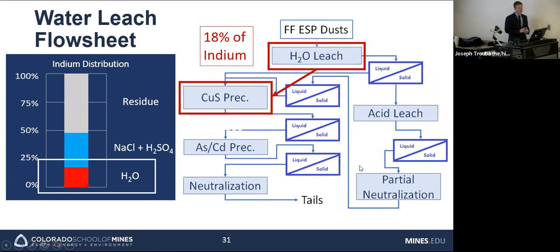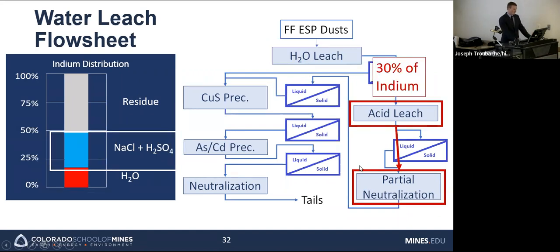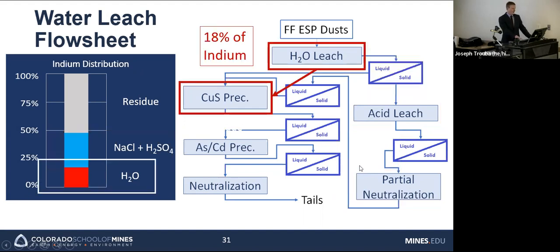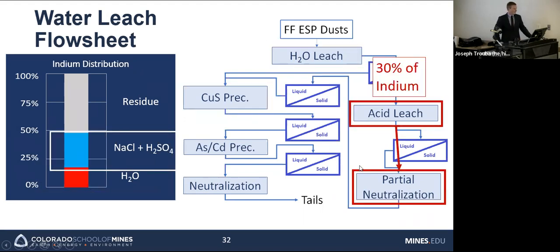According to thermodynamics, the indium should precipitate along with copper and is therefore just returned to the smelter and not recovered. The other 30% that's leached during acid leaching first goes to partial neutralization. If it's precipitated during this step, it would be separated out as tailings, but if it is leached, it goes once again to the copper sulfide step. According to thermodynamics, indium should also precipitate during this step, meaning it's separated from the other streams, and none of these are enriched in indium.